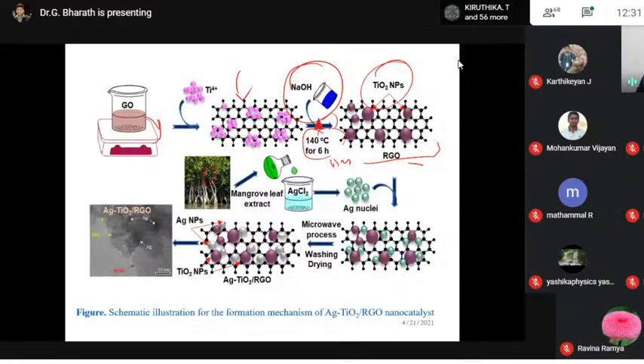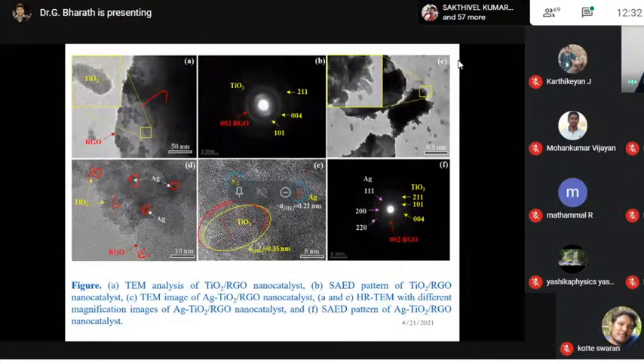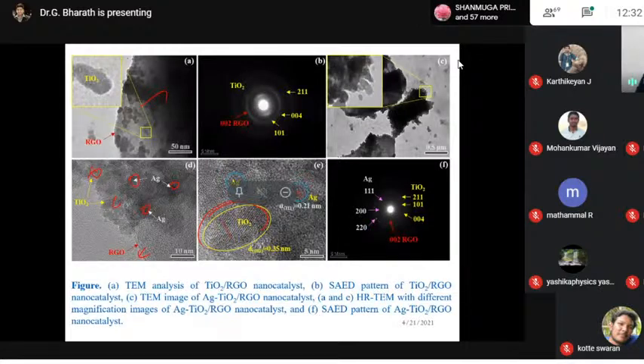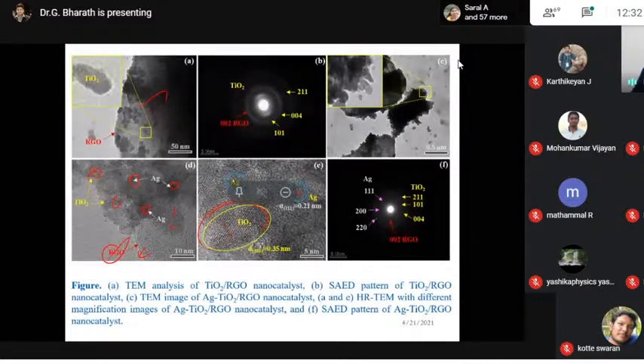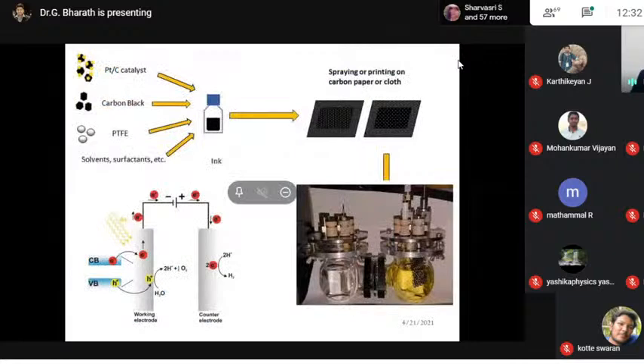After that, we took mangrove leaves. This mangrove leaf extract easily converts Ag+ to Ag0 nuclei. These Ag0 nuclei mix with the titanium and the RGO. This Ag also forms near the TiO2, and after the microwave process, we obtained the Ag-TiO2-RGO nanocomposite. So this is the hybrid, this is pure TiO2 and RGO nanocomposite, this is pure TiO2, this is RGO, this is TiO2, and these nanoparticles are Ag. From the high resolution spectrum, we confirmed that we successfully formed TiO2 and Ag nanoparticles on the surfaces of RGO. This is the photocathodic material for converting CO2 into fuels.